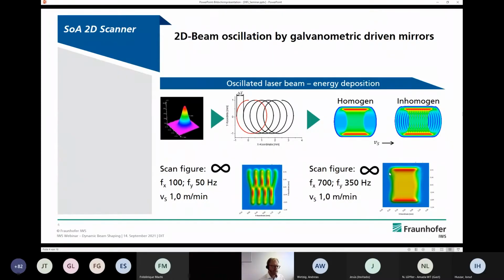If we are talking about 2D beam oscillation with galvanometer-driven mirrors, we usually use fine laser sources, for example single mode fiber lasers with Gauss mode, and oscillate a circle, for example, overlaying it with the welding speed. Depending on frequency and welding speed, we obtain different energy depositions, which could be homogeneous or inhomogeneous, and we usually calculate this with a specific software tool before starting the welding process. The same is the case for scanning a figure in the shape of an 8, again using different frequencies or amplitudes to modulate the energy deposition, as shown here. So we have a lot of variety to interact with the laser beam and the material.